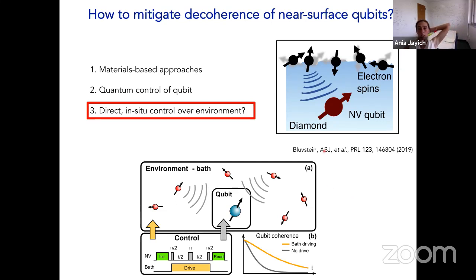Okay, so how does one mitigate decoherence of quantum systems? One can take a materials-based approach, sort of what Bill Phillips was asking. How do we clean up the material, make it more pristine, clean up the surface? There's ways to do that. You can etch the surface. You can terminate the surface. Those are good approaches, but not always super long term, right? If you're using your NV center in some environment over time, the surface is going to get gunked up. So that's not always the best solution.